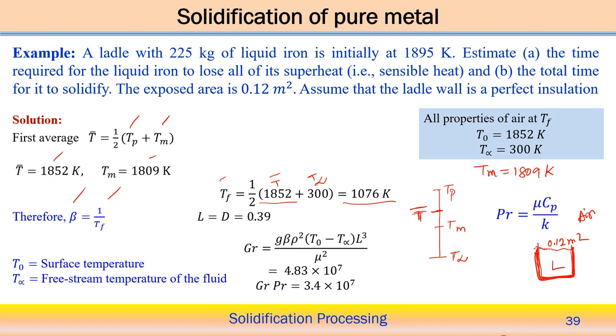Now, in this case, on the top surface, the ladle shape is usually cylindrical. So, therefore, the characteristic length is equal to the diameter of the cylinder. The diameter indicates the equivalent characteristic length in this case. So, L equal to D equal to 0 point, because here the cross section area is given. So, pi by 4 into D square is 0.12 meter square. From there we can estimate the value of D, and that D is equal to 0.39 meter. So here L equal to D equal to 0.39 meter in this particular case, that means we can calculate the characteristic length. Now we can estimate the Grashof number here.